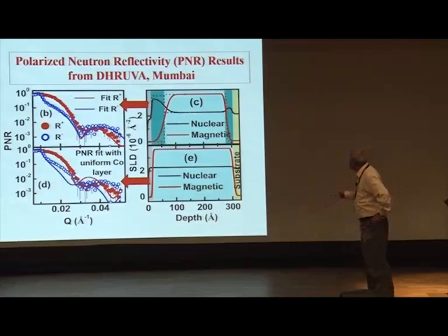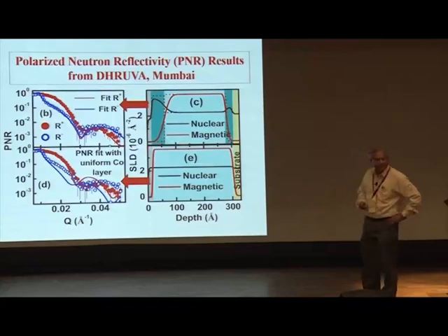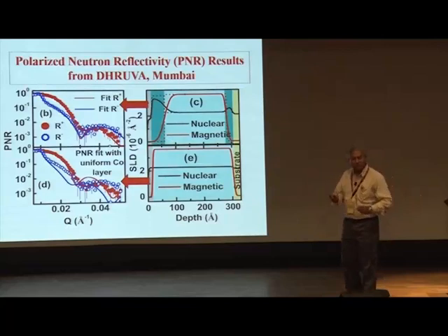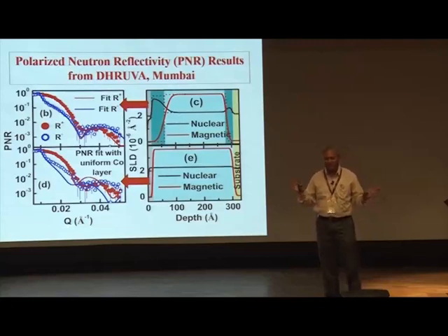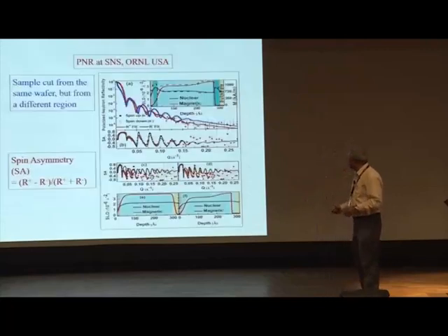Now this is the density, it corresponds to this one. But the magnetic moment density is this one. If we take a normal cobalt magnetic moment density, it doesn't fit. But if you take this moment density profile, that means moment going to 0 here and here, we get this very good fit. So now with these two experiments, we have established that we have high density layers which are also non-magnetic. We have carried out many other experiments to cross-check these results.